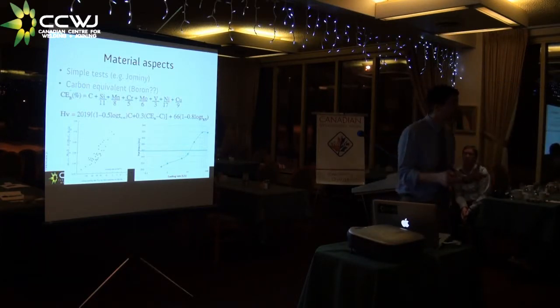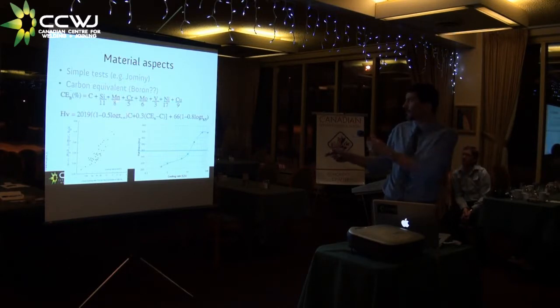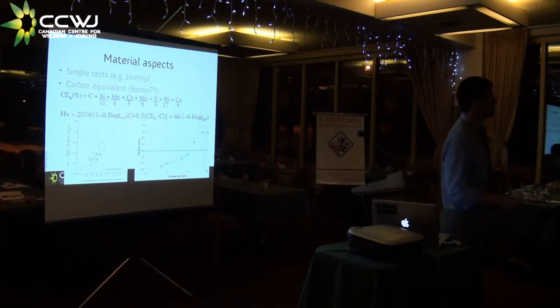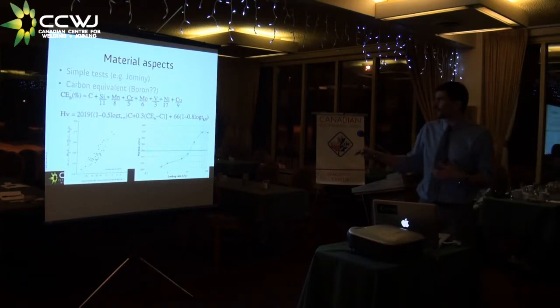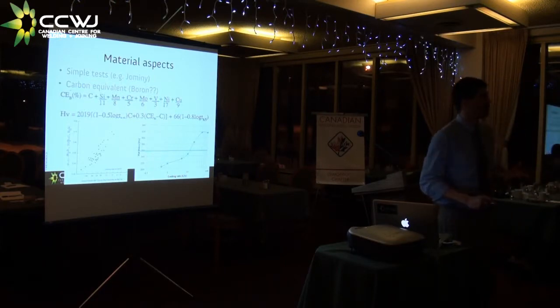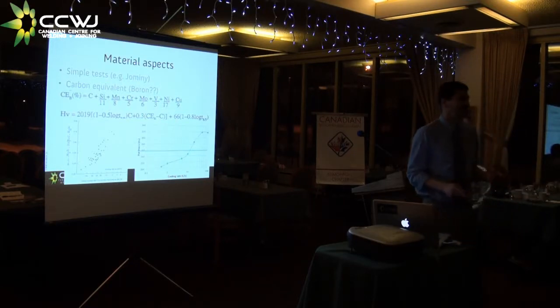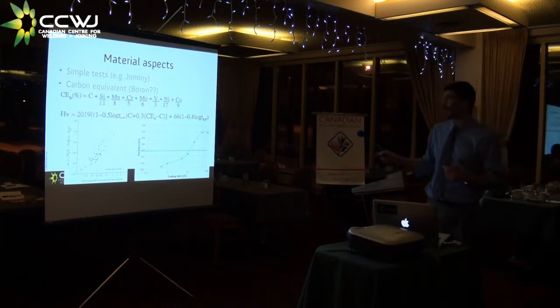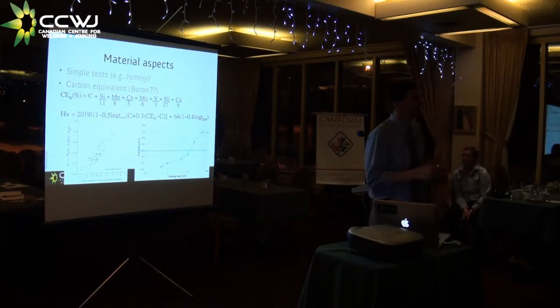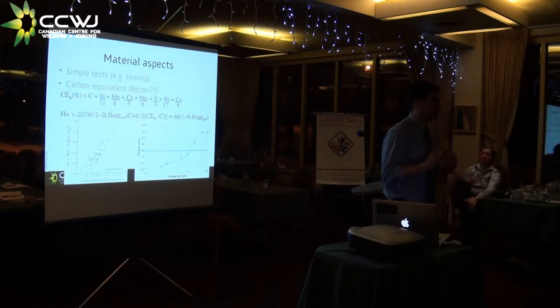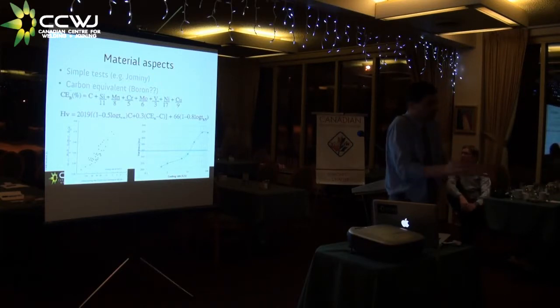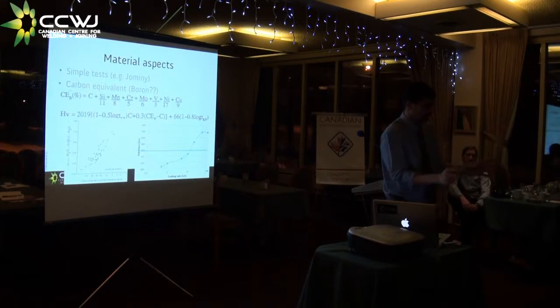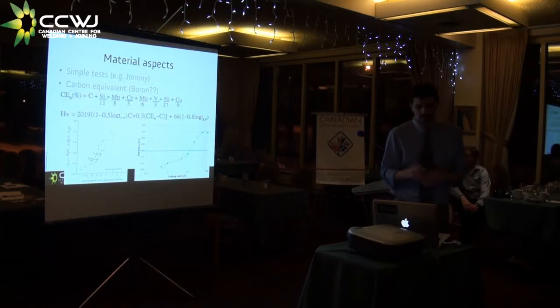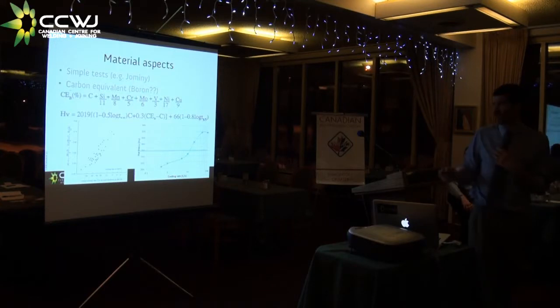Now, there are limitations to this. For example, these two formulas that I got from the CWB Module 21, where is the boron? If any of you had to play with boron steels, you know that those guys get hard in the brush, right? So all these things need work, especially when we say here in this province we work with not an infinite variety of materials, but some variety that nobody considers seriously and with a good focus. So things like this carbon equivalent, I believe, needs to be revisited for what we care about here in the province.